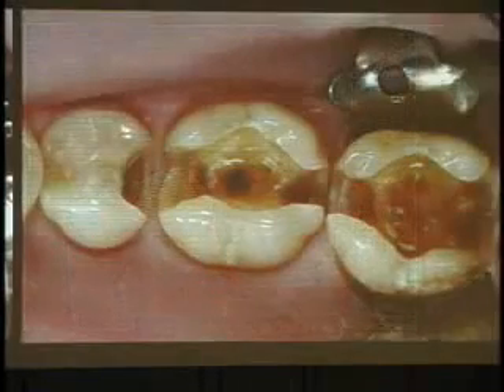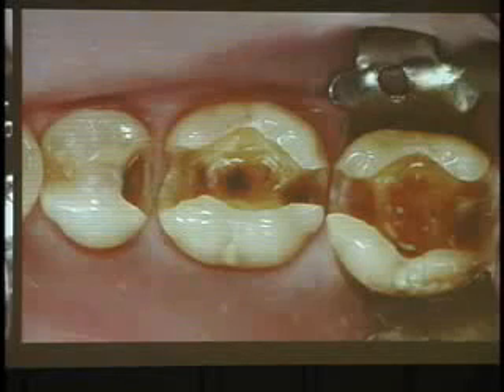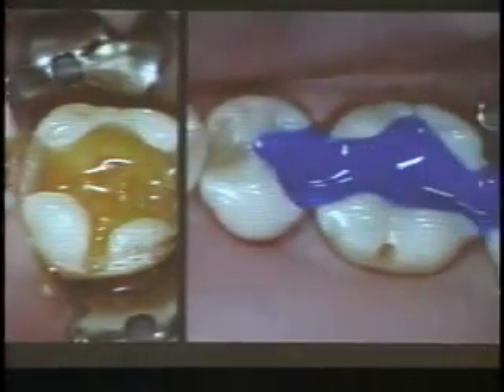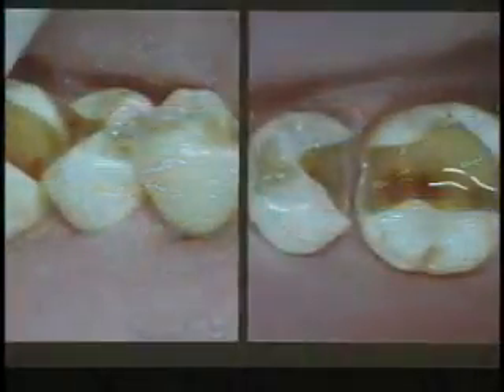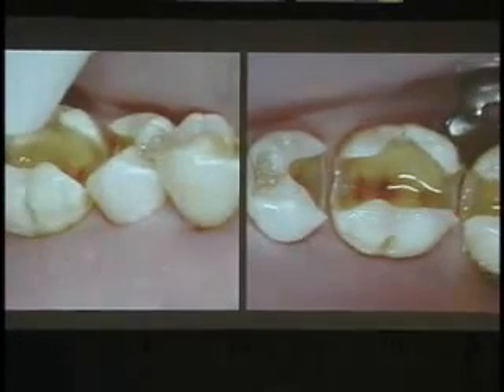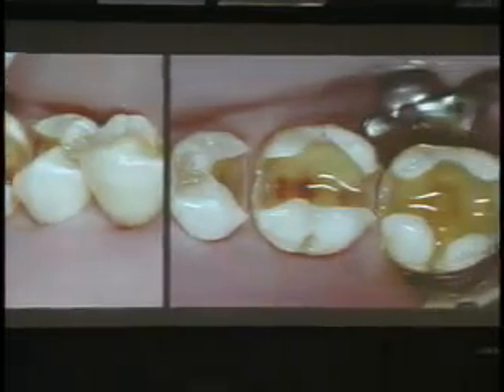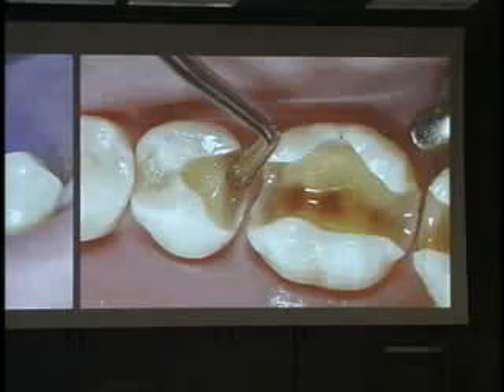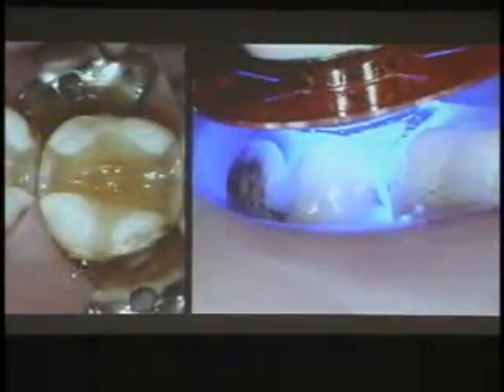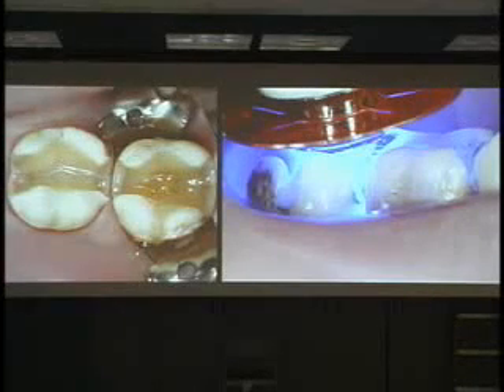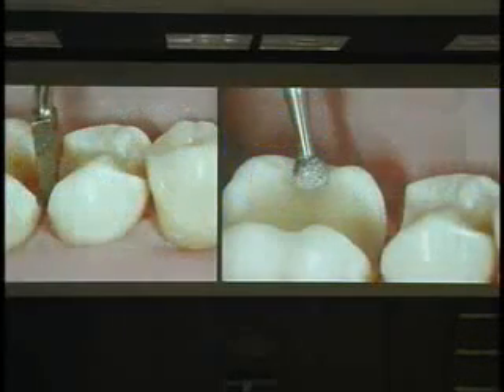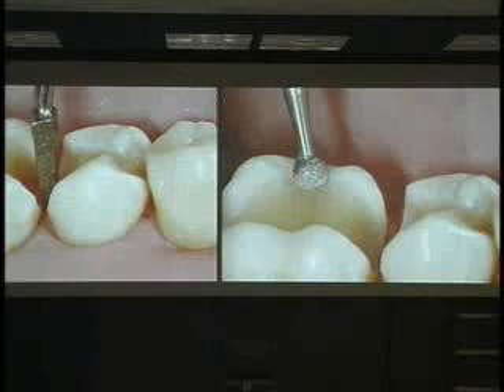That makes a huge difference, and that's the last case I'm showing you today, a case where we removed 3 old restorations with recurrent decay. That's before cleaning, after cleaning the decay. Then we etched dentin, we applied a primer, we suctioned the solvent from the primer, we applied the adhesive resin to the cavity, and you see I still have lots of undercuts. So I'm going to now fill the undercuts with composite resin, cure the resin, all the undercuts are filled, and now I air block the surface of the resin, I cure again to avoid the inhibition layer, and I finish the margin with the oscillating tips in the proximal, burrs in the occlusal, and you are ready now to take your impression.